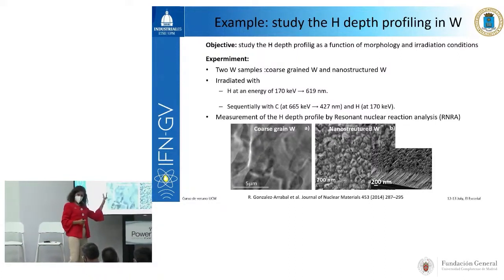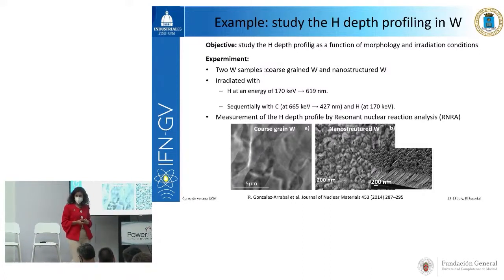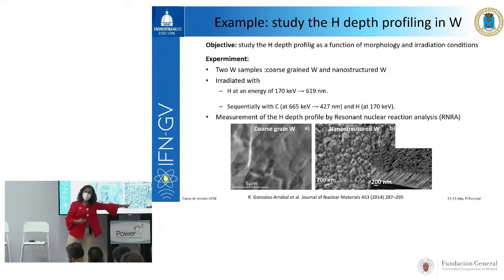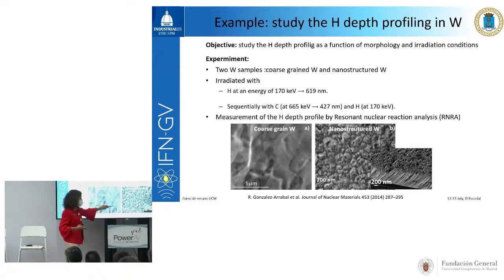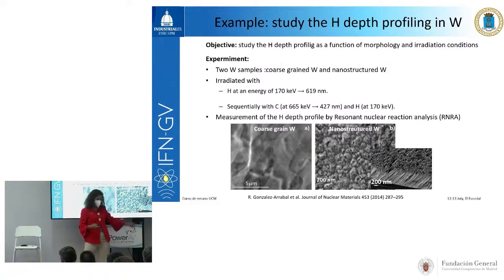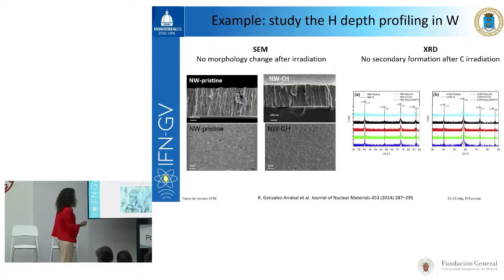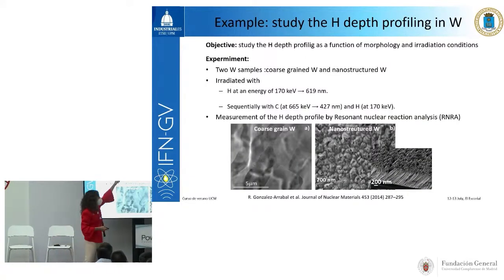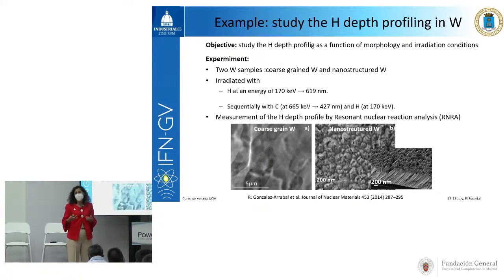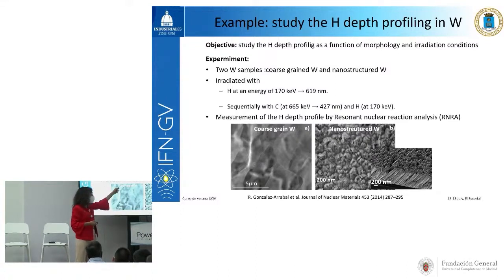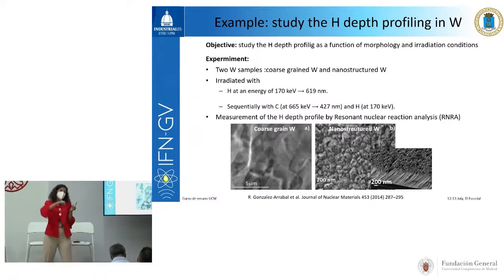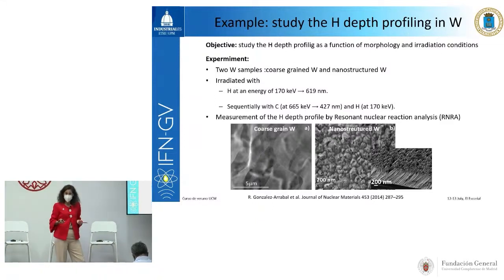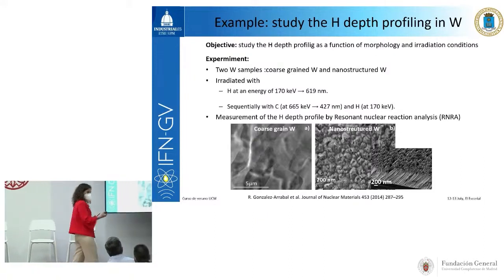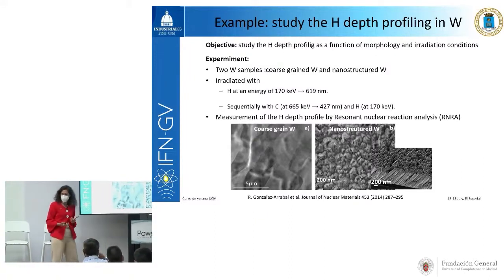Basically, in this particular study, we were studying coarse-grained tungsten, so commercial tungsten, and we were studying nanostructured tungsten, which was deposited by us. It was deposited by sputtering, as the one you may see here. So basically, we aim to study the hydrogen depth profiling as a function of the morphology and as a function of the irradiation conditions. And then we were characterizing the hydrogen depth profile, so how was the hydrogen distributed in the material, by making use of resonant nuclear reaction analysis, of nuclear techniques. So we use ions to characterize the effect of ion irradiation on the material.